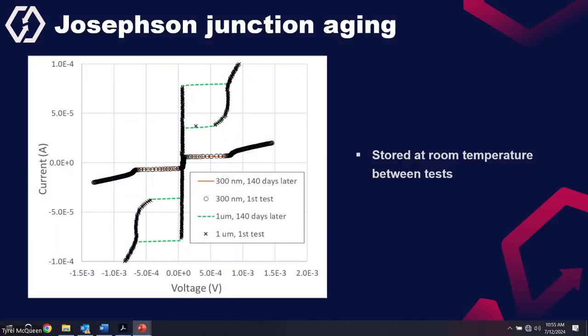Next, we tested the aging of junctions, because in the traditional aluminum oxide based junctions, aging is an important parameter because the aluminum oxide degrades with time. So here we tested the junctions at an interval of 140 days. It shows the same IV characteristics, which means it is stable over time, it is not degrading, which is due to the ALD tantalum nitride being thermally stable. So which is another advantage of using this technology.